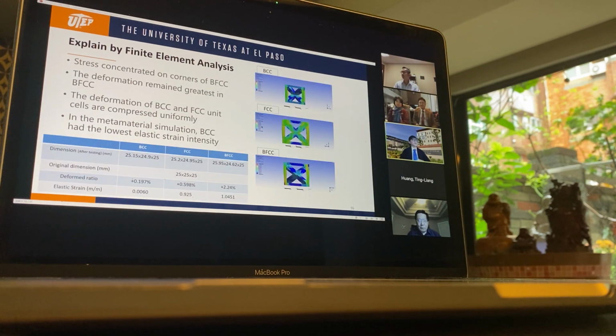Okay. So in the end of this project, we use FEA simulation to validate the deformation results and to have some further understanding of the deformation mechanisms. So in the beginning, we set a fixed corner to make sure the structure cannot be moved and apply the deformation loading with 1 millimeter per minute velocity, just the standard setting of the compressive testing. So the simulation of the unit cell is shown on the right-hand side.